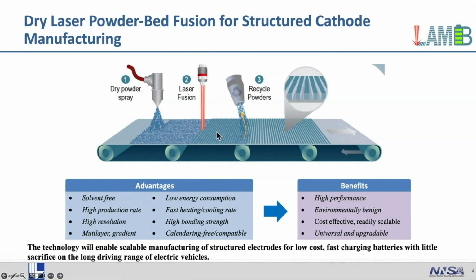So you can envision that you can do some structuring there and some customized shape to give you what you need on the battery electrodes, and you can also do layer by layer coating, and those untreated areas you can recycle the powders for reuse to reduce the material waste. So it has advantages like lower energy consumption. It has a faster cooling and heating rate that can enable some unique tuning of the mechanical or material properties. The bonding strength is pretty good, and you can do multi-layer coating and high production rate, etc.